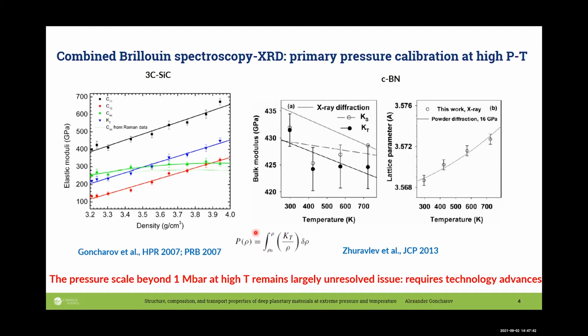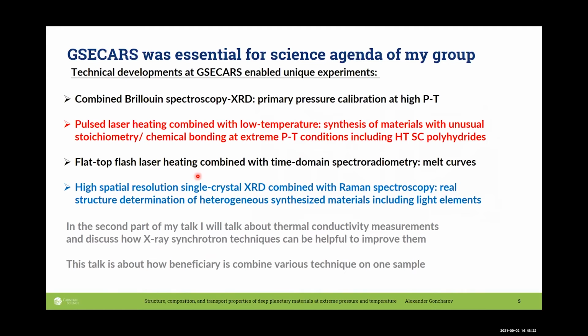But I believe you understand the basic idea. You measure elastic properties, you construct the bulk modulus, you determine density from X-ray diffraction, and you essentially integrate that, and you determine the equation of state and the pressure scale. Now, I believe that work nowadays becomes much more important, and a number of speakers already addressed that. I think that in the future we have to do those experiments in diamond anvil cells with laser heating, and experimentally, we are close to performing that kind of experiments.